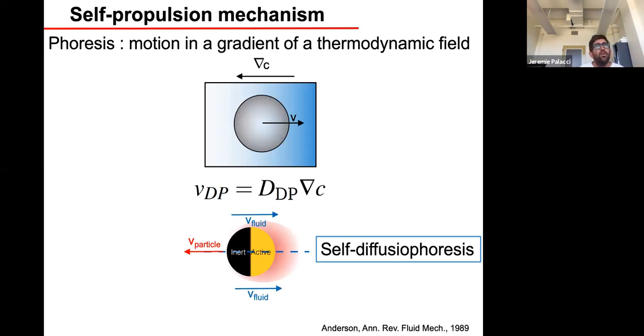I said we have active particles. I didn't say why they were moving. So the way they move is they use phoresis, which is motion in a gradient. So if you put a colloid in a gradient of concentration, it moves by a physical phenomenon called diffusiophoresis. Now if your particle has a chemically active side and a chemically inert side, and you put it in a fluid, it's going to self-generate this gradient. That's a Janus particle, and it's going to self-propel by diffusiophoresis in the gradient it generated. That makes an active particle, and that's basically a strategy that has been used by many people in the last 20 years to get microscopic self-propelled particles.